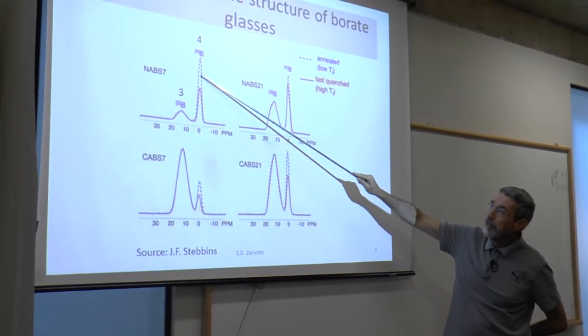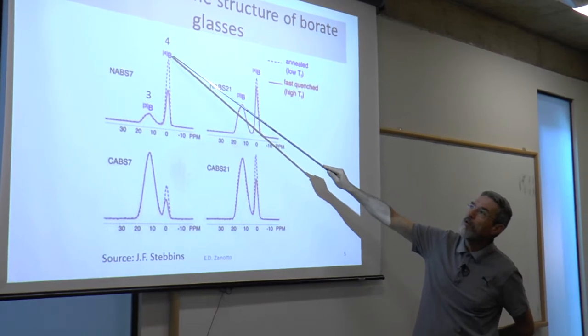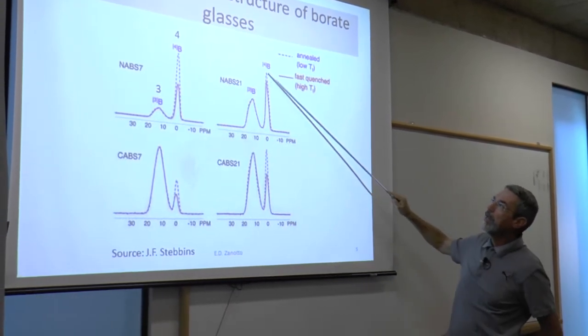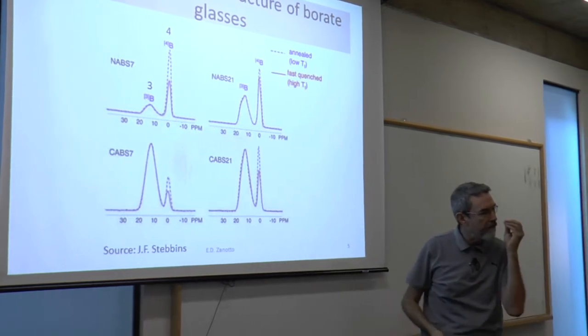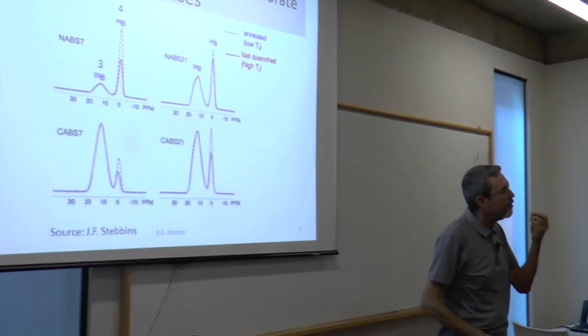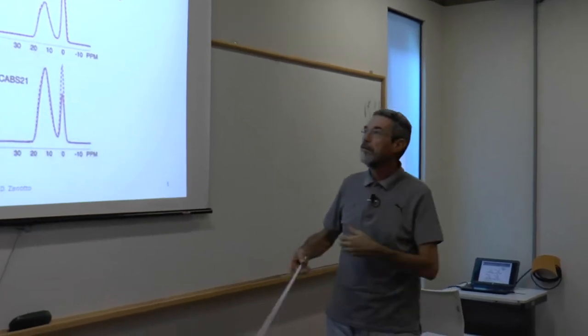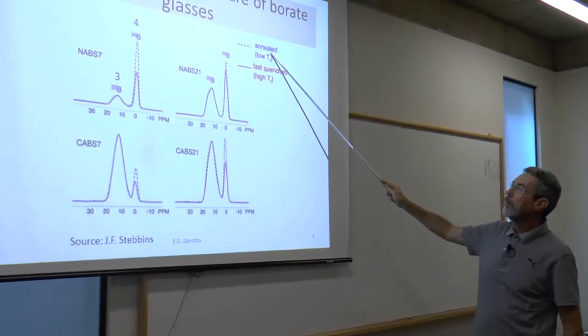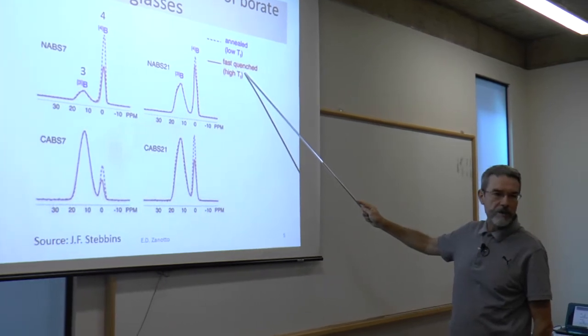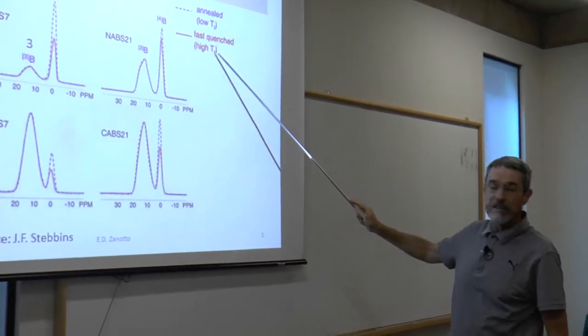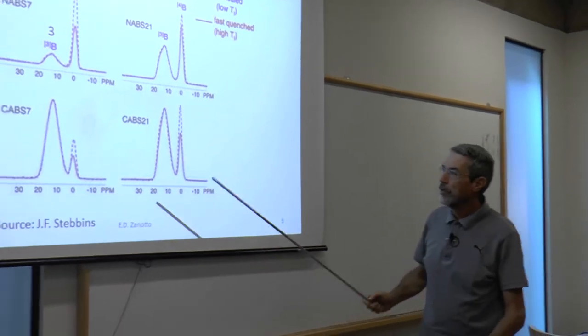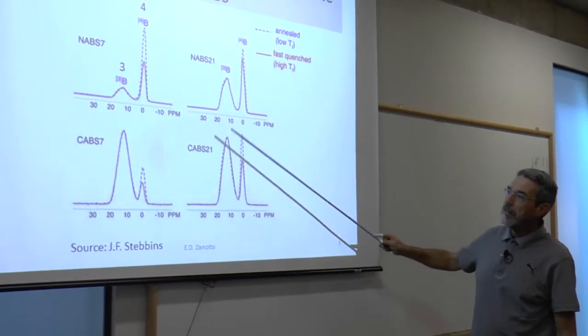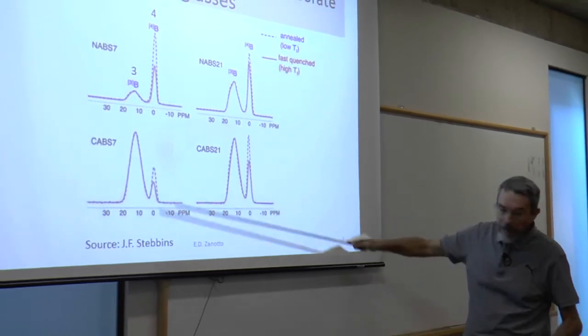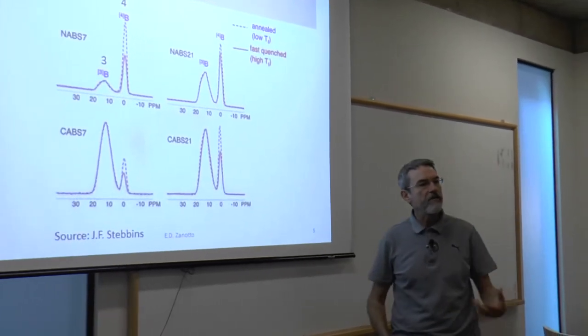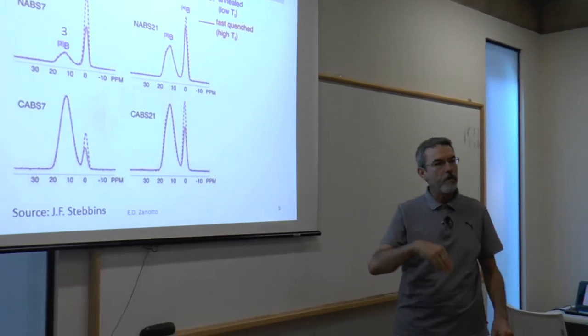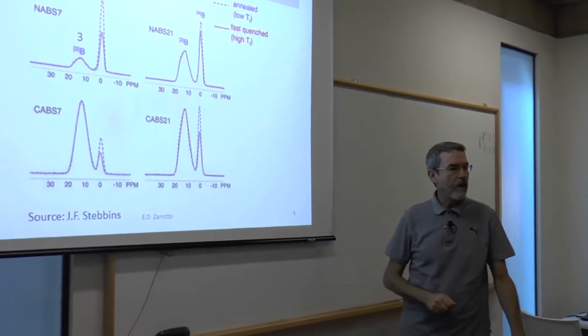If you look here, they have different ratios of boron 4 to boron 3. This is a very fine detail of the structure of an annealed material versus a fast quenched material with high TF. It's the same material. In both cases, you can see that the area under these peaks will give the ratio of boron 3 to boron 4, and they are somewhat different.